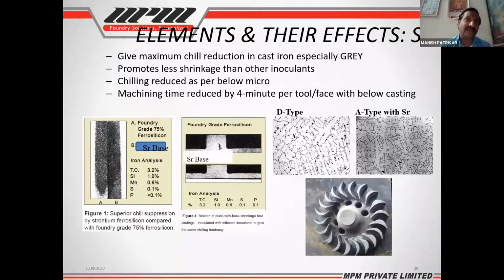For your information, most of the piston ring foundries, which are producing castings with only one or two section thicknesses, are also using strontium based inoculant for SGI. So strontium is not only used for gray iron, it is also effective for SGI. This gives maximum chill reduction. It promotes less shrinkage than other inoculants. It reduces the chilling tendency, and it also improves the microstructure.